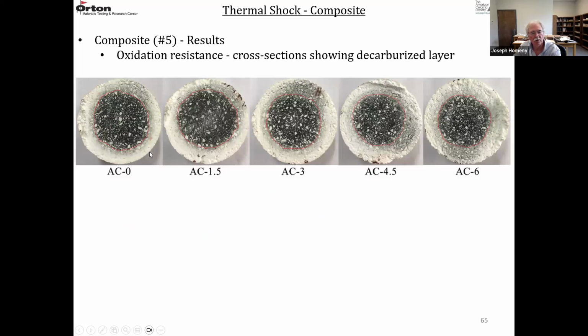So I mentioned they measure oxidation resistance and corrosion resistance. So these are the cylinders that were oxidized in an air environment. These are the cross sections. So the cylinders are cut. The white areas are where the carbon has been oxidized, the decarburized zone. And then the black area is the remaining carbon. So they're kind of circled in red there. They're all, in my opinion, pretty much the same.